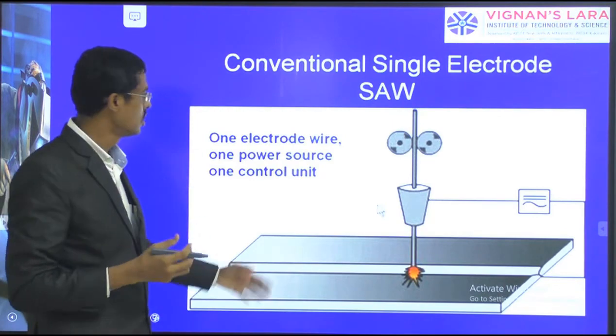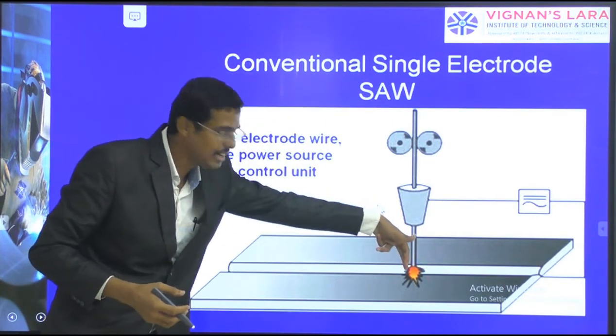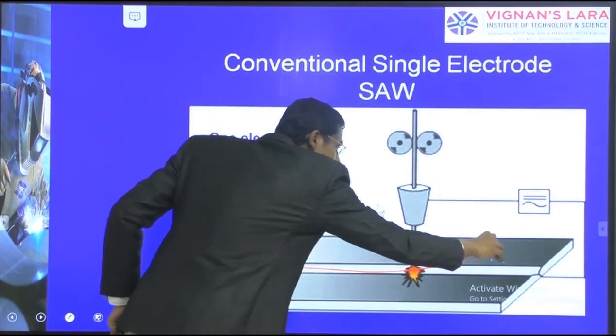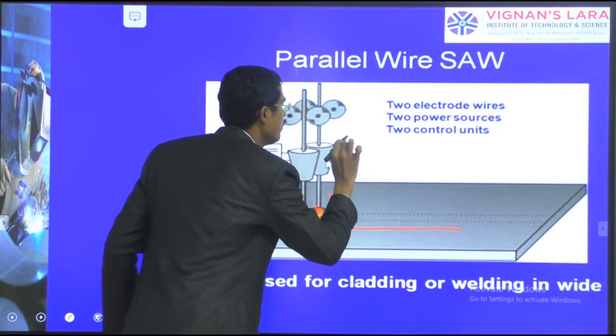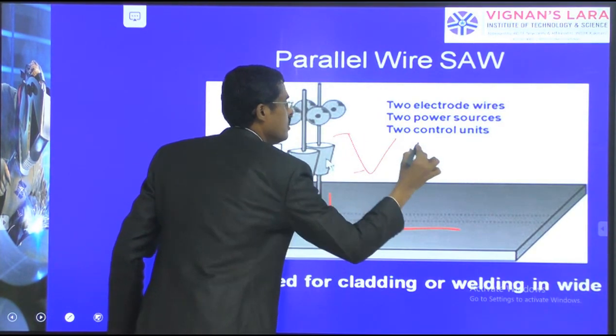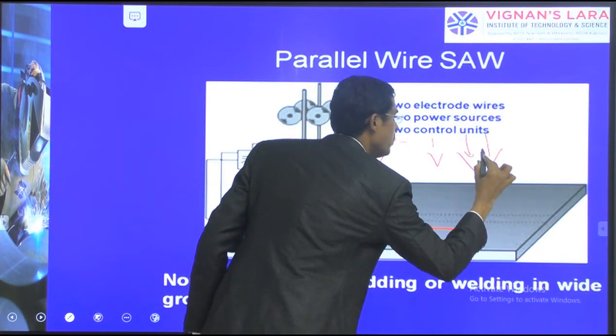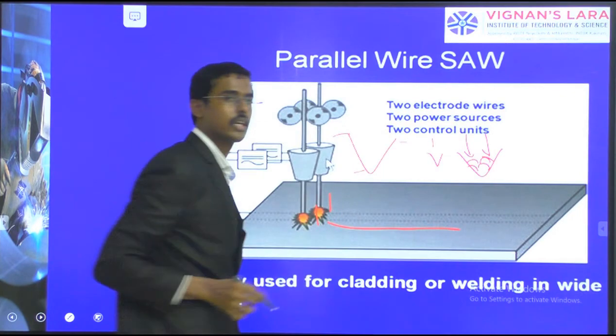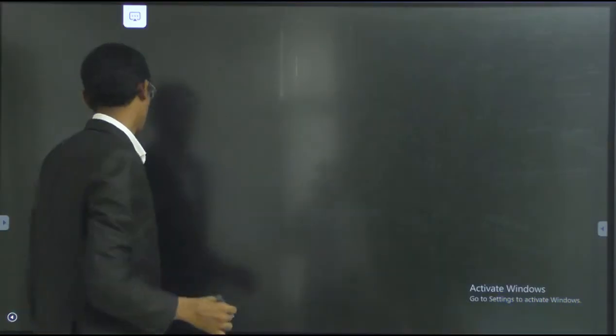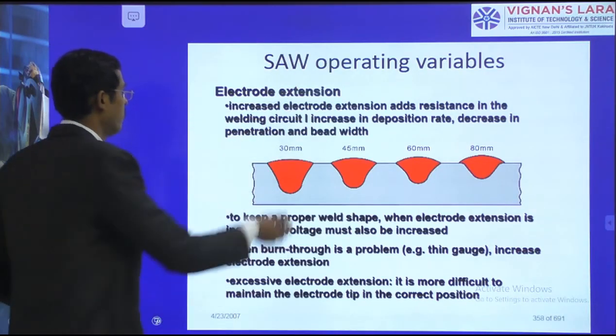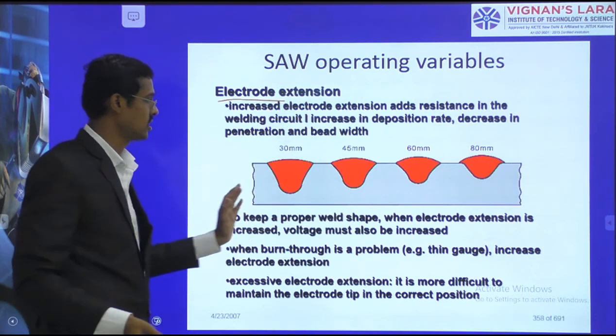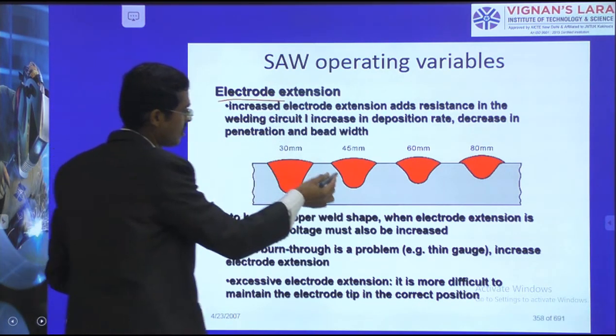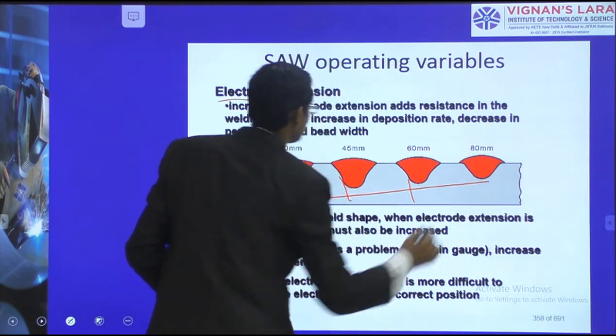So in submerged arc welding we may use a single filler wire, or otherwise we can use double filler wires if the thickness is larger. For small thickness we can use a single wire. For large thickness we can use the double wire methods. Such things we can do in the submerged arc welding process. So, on other electrode extensions, when the electrode extension increases, obviously the penetration also decreases.